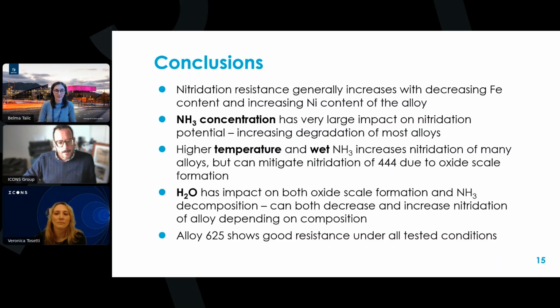Thank you, Belma, first of all, for the great talk. The first one is the addition of additional steam. I completely understand. So you increase the oxygen partial pressure, so we have an oxide scale, which is a barrier against nitridation. But steam is well known to induce chromium evaporation also. So how does that correlate to your mass gain data? So we are, on the one hand, mitigating nitridation, but also we are evaporating chromium out of the alloy. The second is actually a funny question. So I saw that you're using 316L tubes. So do you inspect any damage on the tubes, or how often do you need to change them?